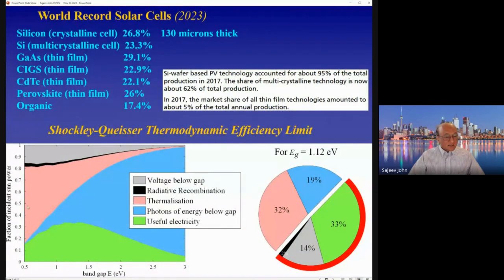So this is a plot showing where the energy that comes from the sun ends up as a function of the band gap of the semiconductor. So the blue region corresponds to photons that lie below the band gap of the semiconductor. As the band gap increases, more and more photons are unable to be absorbed, and so they just get reflected. On the other hand, if the band gap of the semiconductor is made much smaller, then a lot can be absorbed, but the electron that is excited by absorbing a photon goes up very high in the conduction band and quickly relaxes by thermalization down to the bottom of the conduction band, and that is this pink region.